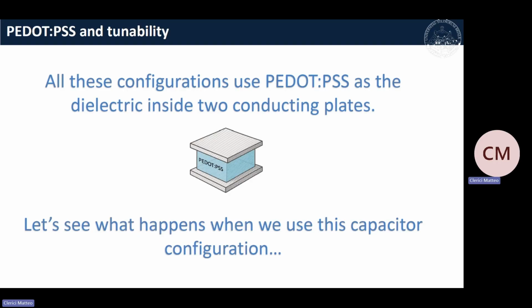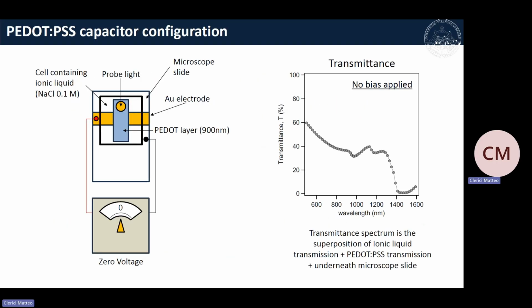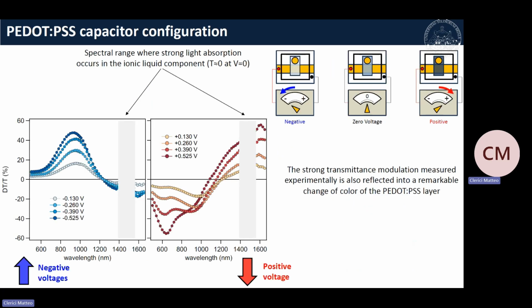When you sandwich PEDOT:PSS between two electrodes, as they did before, you start from a situation where you have no bias applied. You have one electrode below and one electrode on top that is placed in the electrolyte, and you start with about 50% transmission in the visible range. Then you apply a negative voltage, and if you look again in the visible and IR, you see that your differential transmission goes up. If you apply a positive voltage, you see your transmission go down. So basically your PEDOT layer is turning lighter or darker depending on what you're doing.